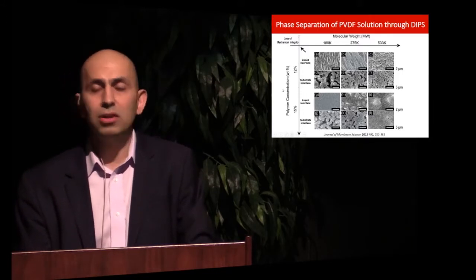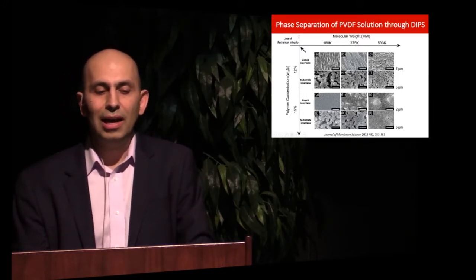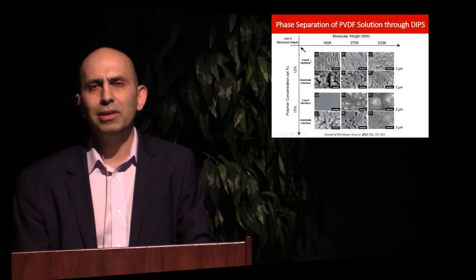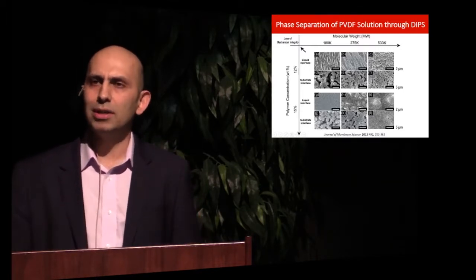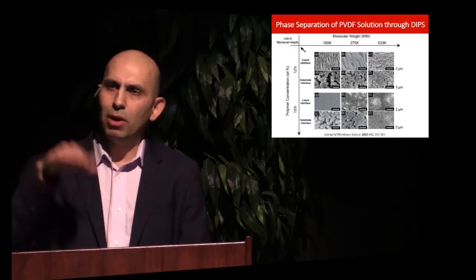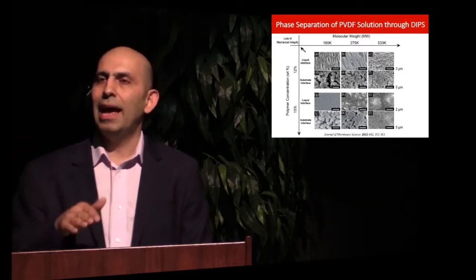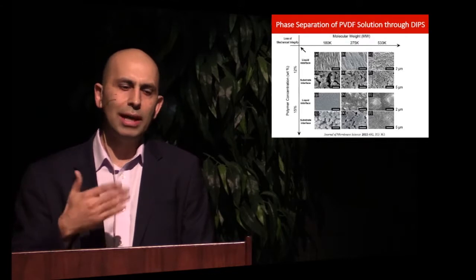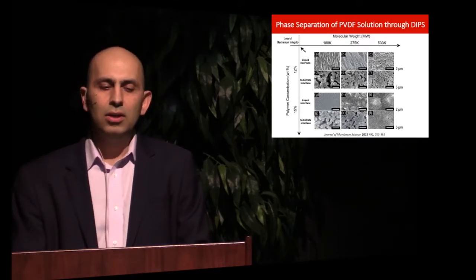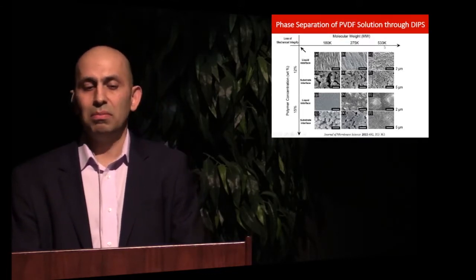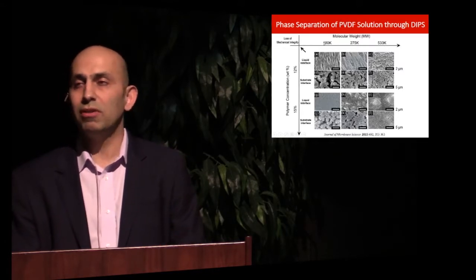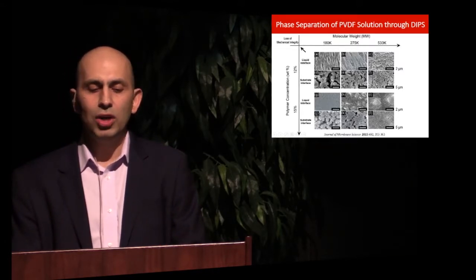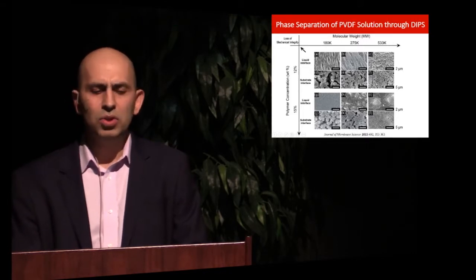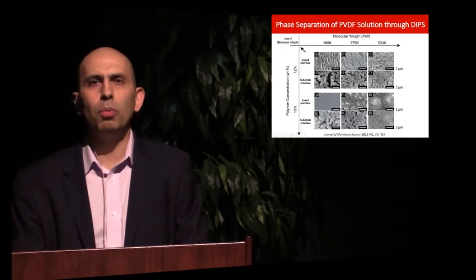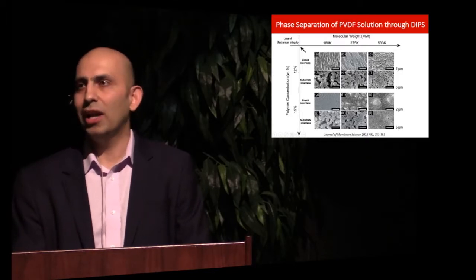Here's our first attempt. We looked at molecular weight, and we looked at the concentration of that solution. When we do that casting process, whatever is at the interface of the liquid polymer is called the liquid interface. And whatever is sitting on the substrate, we call the substrate interface. You see, as we change the parameters of this process, such as molecular weight of the polymer or concentration, the structure significantly changes. Most of these things are closed. Basically, there are no pores. So that was the first challenge we faced.